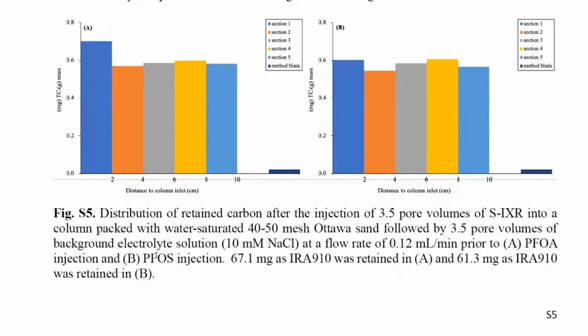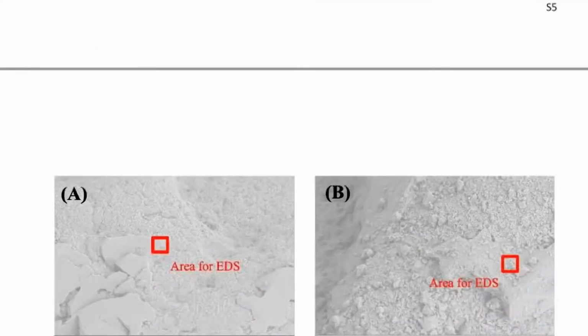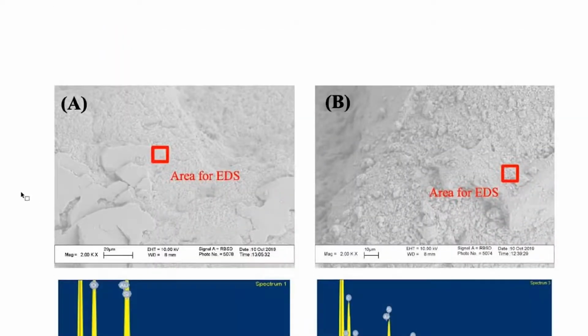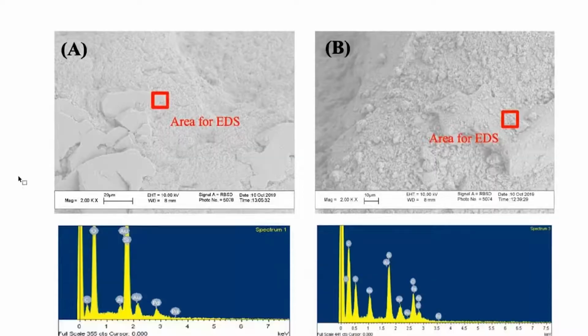And last thing I want to show you that is probably the most convincing is we did some SEM imaging before and after. So this on the left is before. So this is a sand grain before treatment, and on the right is after treatment, and you can see all these little bumps on the surface. And so then, of course, the question is, are these really the beads, or did you just pick a different grain of soil and it is more bumpy than the other one? Which is a good question, honestly.